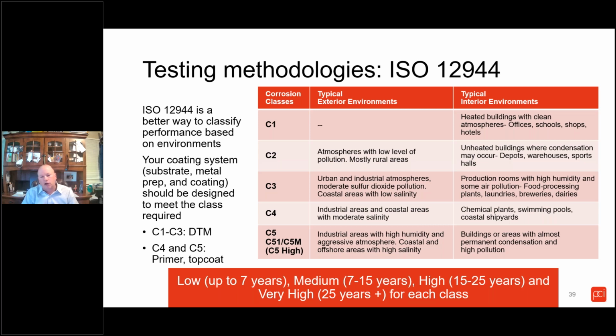Within each of these criteria, the lower end tends to have salt spray requirements, non-cyclic, and as you get into the higher end, cyclic testing. Your coating supplier should understand what tests are required for each level and can direct you in the right direction. Generally, C1 through 3 are direct to metal, C4 and 5 are a primer top coat system.